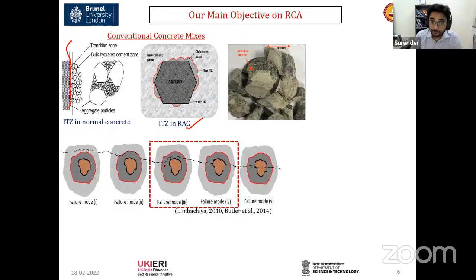That means the weak zones in recycled aggregate concrete will be either the adhered mortar or the interfacial transition zone between the old mortar and the aggregate. But we are the engineers, so we have to engineer this material, like Dr. King has mentioned, tailor-made recycled concrete aggregates, such that we can control this failure pattern. Control means the crack should propagate through the new mortar, so we can control it, right? We can control the properties of the new mortar.